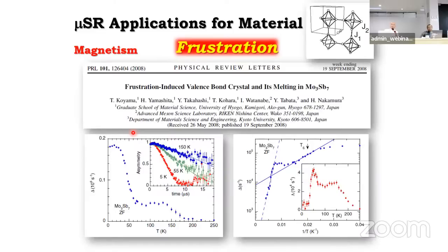This one is also a very excellent result to pick up the lattice vibration by using muons. So the lattice vibration is changing by changing the temperature in this system, but this kind of change cannot be sensed by anything else, because it is a vibration motion of the lattice, so we cannot pick it up by X-ray. We cannot pick it up by neutron. However, this kind of vibration can vibrate the more tiny magnetic moment, then muon can easily pick it up. Then that is changing by changing the temperature. There seems to be two transitions here, the vibration transition here and here. This one is the first report to show such kind of double transition in the lattice vibration in magnetic materials. So then that was published in PRL.